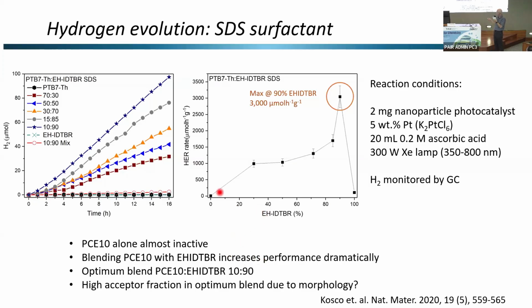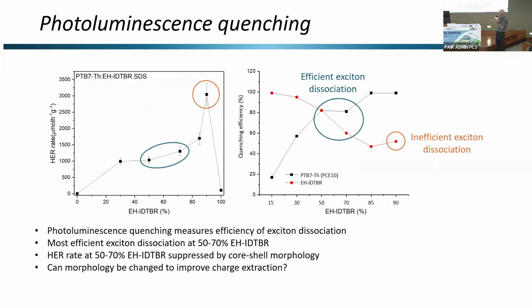So that's a worry. And we can see here, when you look at the HER rate, that's the hydrogen evolution rate versus the fraction of EH-IDTBR, you really need to be up around 90% to get this maximum HER. So when we think about that, what we think happens here at this very high acceptor is that it's kind of poking through the shell in order to allow a very thin donor shell that allows electrons to be able to reach our platinum. But, you know, probably not ideal, because